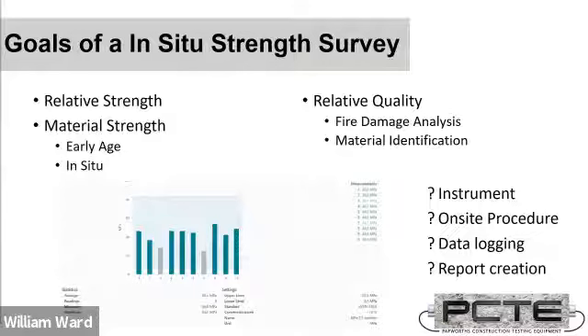You can consider, this is a good time to go on to the next point, looking at relative strength rather than an actual MPa strength. Because Schmidt hammers, the conversions are only so good. But one thing a Schmidt hammer is very good at is determining difference between the same material in different places. The example I always like to talk about is if you have finished one pour with a concrete mix and you've got all of your compressive test records and they're correct, and you then have a second pour and for some reason the samples are lost or incorrectly cast and they're not appropriate, so you don't have compressive strength records for the second pour of the same material, it can be very appropriate to gather raw Q or R values on the known good section and then determine if the second pour, where the results were lost, has similar values, comparing relative strength. So they should be very similar if it's the same mix under the same conditions. And if there's a difference there, then maybe it needs further assessment.